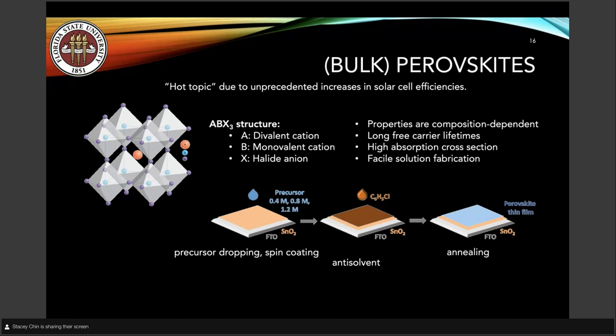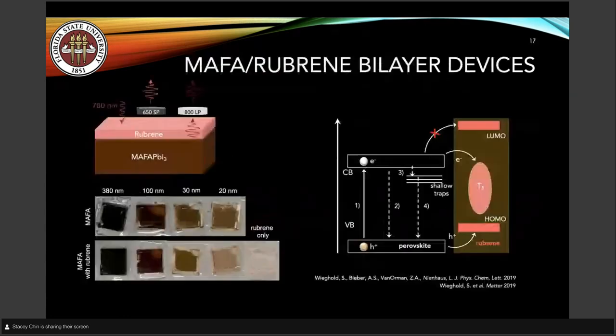Conveniently, your properties are, of course, composition dependent, so you can tune the band gap based on your composition. Perovskites generally have long free carrier lifetimes, which essentially will allow our charges to live long enough to be extracted. They show high absorption cross sections, and they're very easily solution fabricated. So in our case here, we're doing methylammonium formamidinium lead triiodide perovskites, which we name MAFA for convenience. And our upconverter is rubrene, just a tetracene derivative.